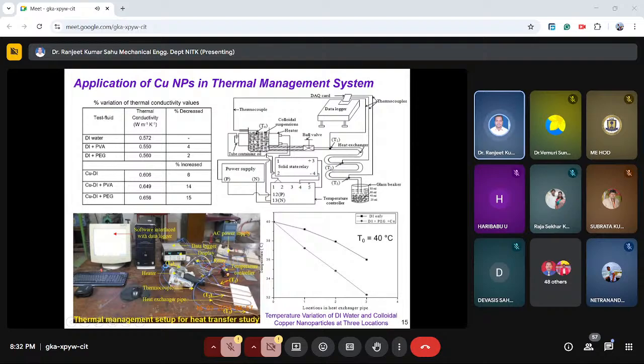Similarly, we use these copper nanoparticles which are produced in PEG solution, heated at the same temperature, passed through the heat exchanger and collected in the glass beaker. You see, from this figure it can be found that the heat transfer capability of this copper nanoparticle dispersed in PEG solution is more effective as compared to the DI water.